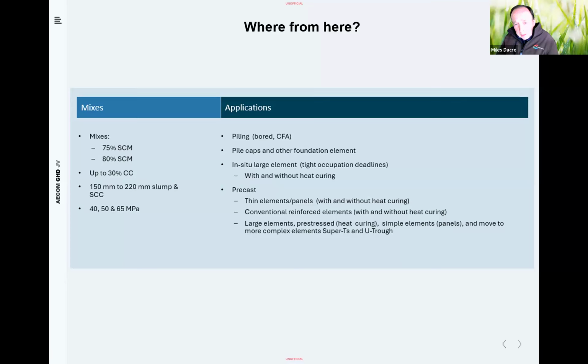So our thinking around this is all those applications would suit the concrete type mixes on the left hand side. So 75% SCM, up to 30, possibly 40% certainly for the shotcrete. So we're trying to get into a range of mixes which are quite confined, but can be used on all those elements, so that if we do the different trials on those elements, then we can cross-reference the data and compile it more quickly.